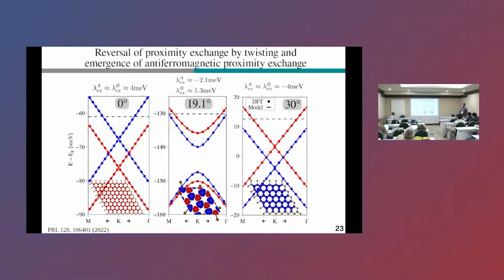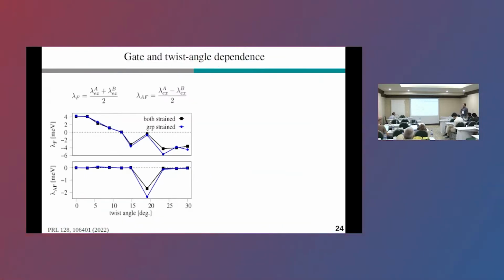And what is even more remarkable is that at a certain twist angle, this 19.1 degree, you can actually realize antiferromagnetic proximity exchange in graphene. As we can see here, this very nice sublattice character of, say, positive and negative spin polarization on the graphene. And of course, we did not only investigate these three angles, we did the full angle range scan. And what I summarize here is the ferromagnetic and antiferromagnetic proximity exchange as a function of the twist angle. And what we can see here is that the ferromagnetic one can be tuned rather nicely from positive to negative values when twisting from 0 to 30 degrees. This antiferromagnetic proximity exchange arises only for this special twist angle of 19.1 degree.